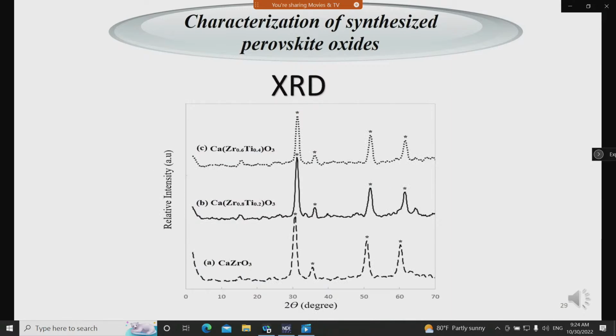The X-ray diffraction analysis was carried out for all prepared samples. The diffraction peaks of the synthesized perovskite are in agreement with the patterns previously reported for these samples. And the lack of signals for titania and zirconia also proves there is no oxide impurity in the supports.